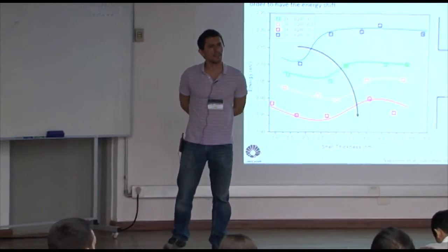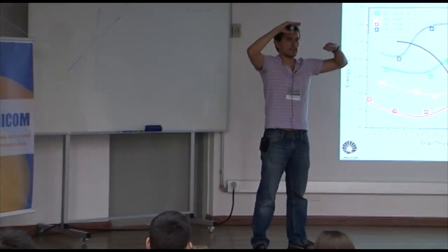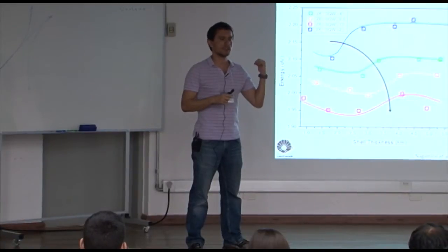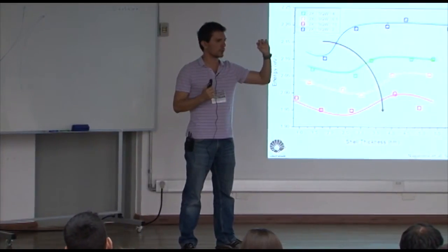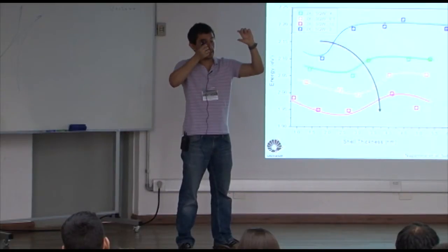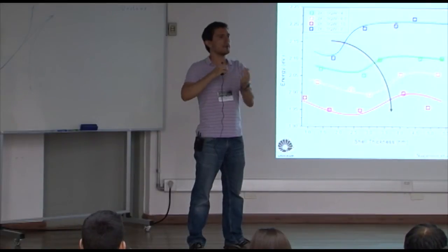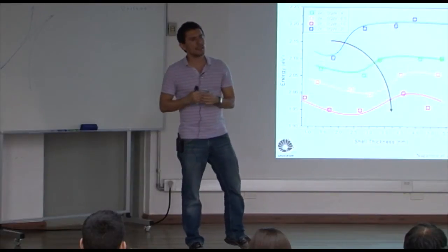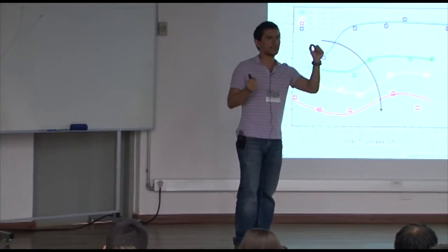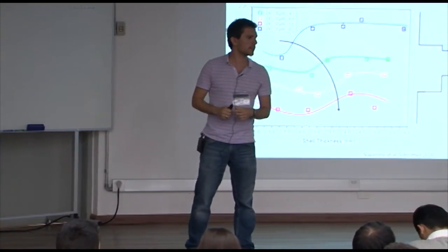or if you want to make a sharp interface. There is another story that I'm not going to tell today, but when you make a very sharp interface, like you finish with cadmium selenide and start with cadmium sulfide, really sharp, similar to what happened for the carrier multiplication, you can lock the holes in the shell in a way that the shell starts to emit. So you can have a material that emits in the red because of the cadmium selenide, and then eventually emits in the green because of the cadmium sulfide. By controlling how much you excite it, you control whether it emits in the red or the green. From that, we were able to make a dual-emitting LED. By controlling the power, the current, you change it from red to green. It's pretty cool. This is basically interface engineering.